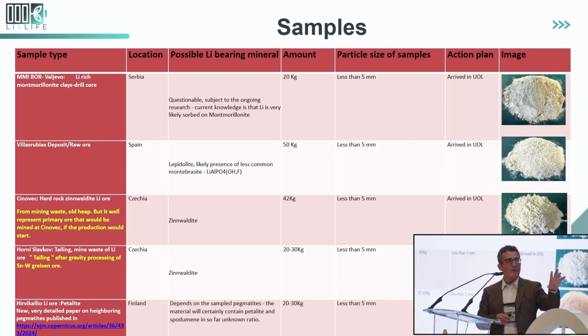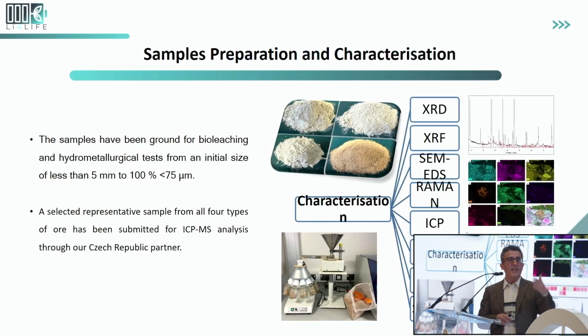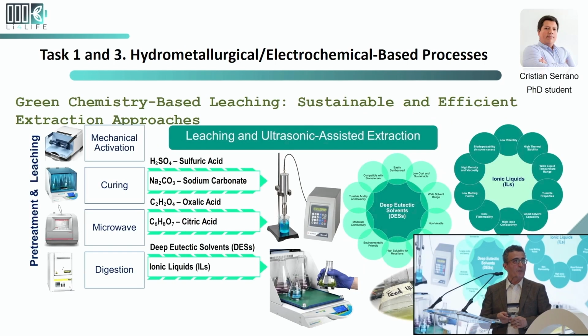And these are the samples we have already gathered, and we received the samples after our partner in Germany or another country ground, crushed, and did the initial sampling. We get them after flotation or directly from primary resources, and then we apply different initial characterization: XRD, XRF, SEM, EDS, Raman, ICP, and also FTIR. We also use simultaneous thermal analysis combined with mass spectroscopy to see, if we're using thermal processes, what happens during the process.